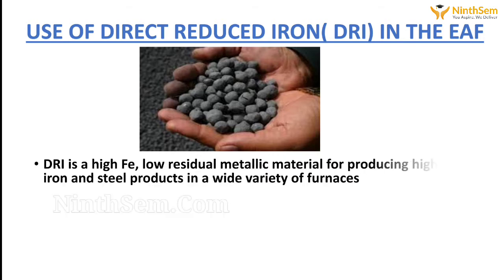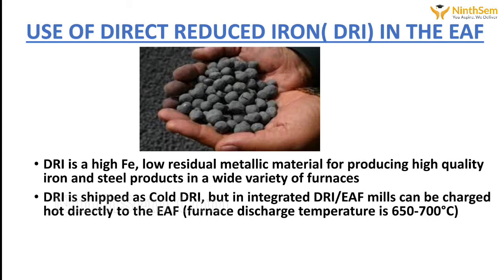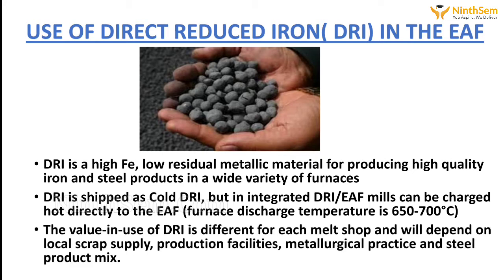DRI is a high Fe, low residual metallic material for producing high quality iron and steel products in a wide variety of furnaces. DRI is shipped as cold DRI, but in integrated DRI electric arc furnace mills it can be charged hot directly to the furnace. Furnace discharge temperature is 650 to 700 degrees centigrade. The value in use of DRI is different for each melt shop and will depend on local scrap supply, production facilities, metallurgical practice, and steel product mix.